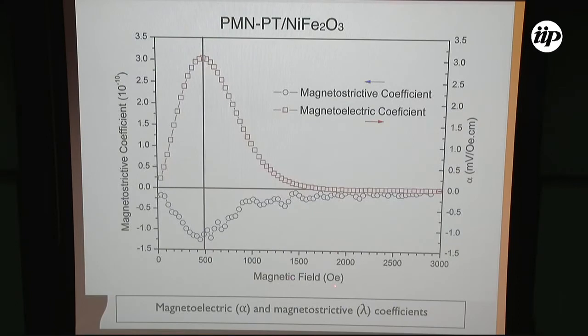So it's possible to obtain this curve, which is a typical curve of the PMN-PT/nickel ferrite. In the red curve, the magnetoelectric coefficient is observed, and in the blue curve, the magnetostrictive coefficient. It's very interesting: the maximum of the magnetoelectric coefficient is at the same position as the minimum of the magnetostriction. So this result shows a direct coupling of the ferromagnetic phase with the ferroelectric phase in this material.